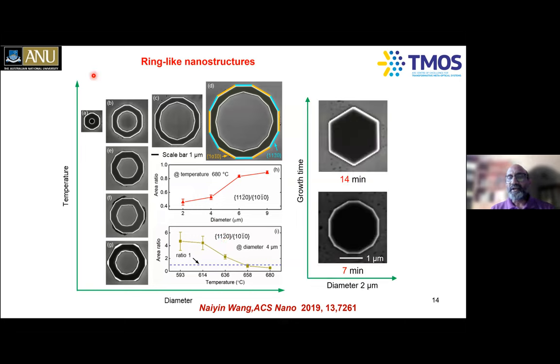And if you keep on growing, then what happens is that this gap in the middle gets filled up and you create a horizontal membrane. If you keep on growing further, you end up having this nice hexagonally faceted membrane again, because of the fact that these crystals like to form the low energy facets, and that's why they end up creating these nice, beautiful hexagonally faceted membranes. Again, as I mentioned, these membranes are very useful for MEMS applications also.